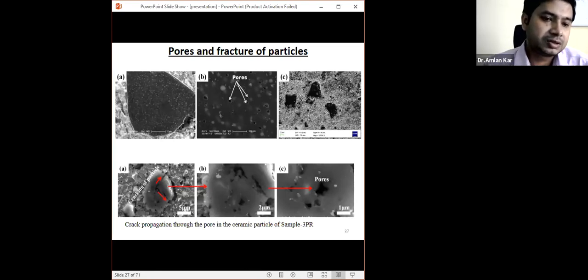So basically, because of this fine distribution of the particles and because of the pores, cracking of the particle takes place during the deformation, and therefore we obtain a fine particle distribution in the final composite matrix.